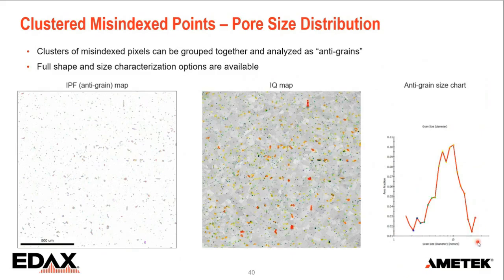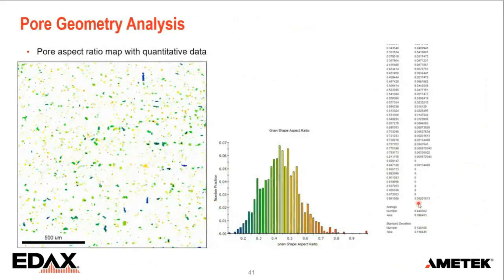You can highlight that. So you just give a color coding on the chart. You can see the pore size distribution in my map. Small, blue, red is very large. And once you have that, you can do all kinds of geometrical morphology analysis also on the pores. So it's grain shape, aspect ratio, for example.